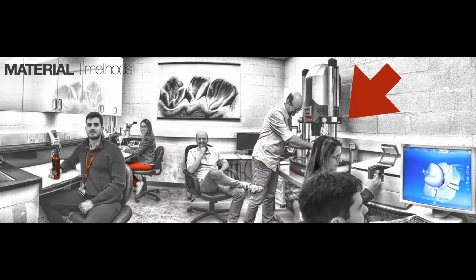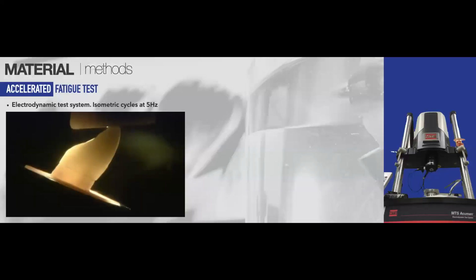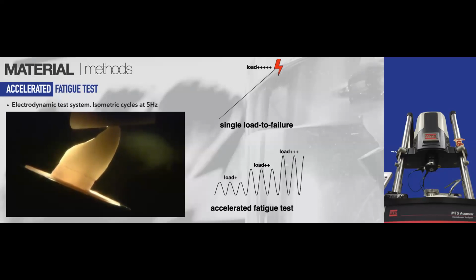So guys, the only thing I want to talk to you about the accelerated fatigue test is that there is a huge difference between the single load to failure, which is the most common test used, where you apply a single force until it breaks, and the accelerated fatigue test. In the accelerated fatigue test, we increase the amount of load as we increase the number of cycles. Okay, so that's more similar to what we do in our mouth.